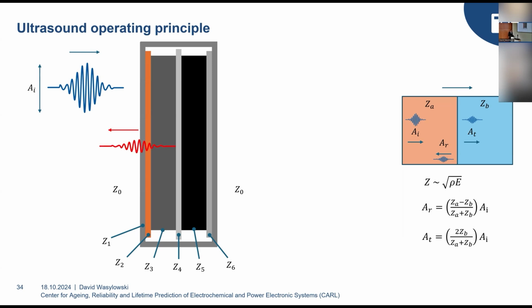So the biggest material mismatch we have in our apparatus is the interface between the silicone oil and the cell housing. So we go from a liquid material into some solid, so very different acoustic impedances, and we get a pretty large reflection at this interface. And then we need to subtract this reflected amplitude from the incoming amplitude, and we end up with this transmitted ultrasound wave in the middle.